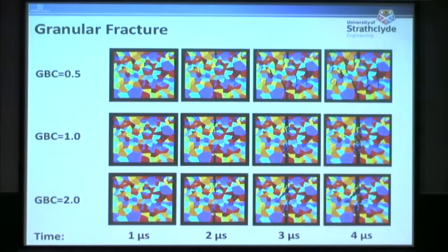And this is just a final plot for me to show that depending on the strength of grain boundaries, we can capture either intergranular or intragranular fracture patterns in a pretty straightforward manner.